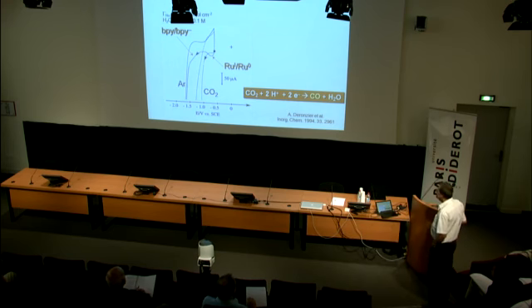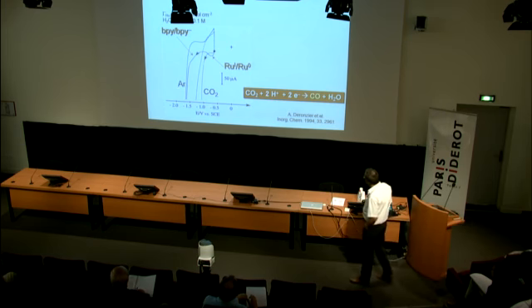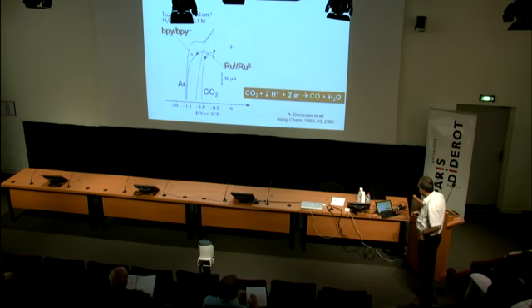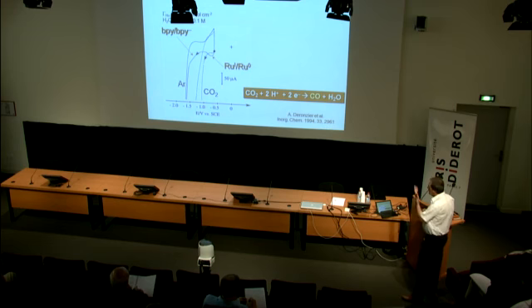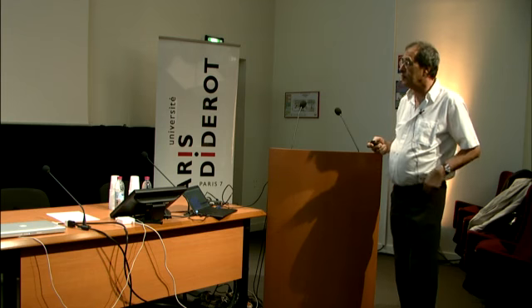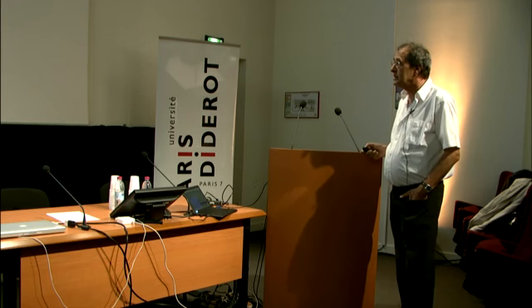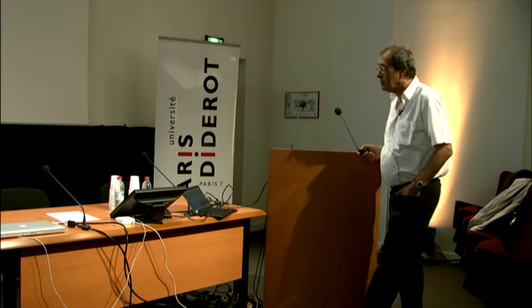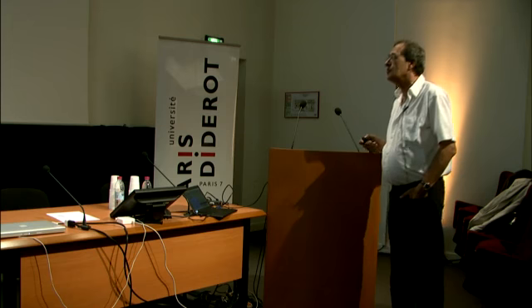What happens if you saturate the solution with CO2? You can see a very huge catalytic current over there, with a shift of around 500 millivolts in the direction of positive potential. So it was very impressive at that stage, and to confirm the electrocatalytic activity of this kind of film, we investigated in detail long-term electrolysis of this system, and we demonstrated that CO2 is selectively reduced following a two-electron, two-proton process into CO.